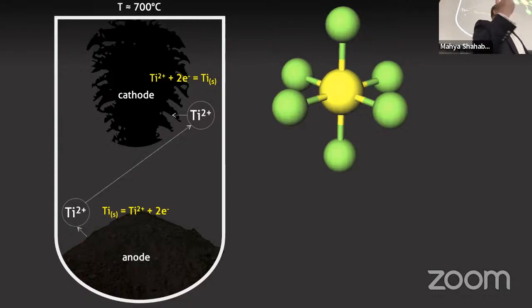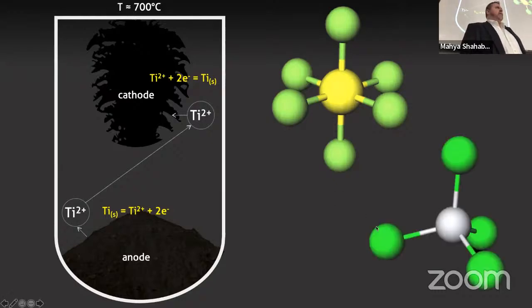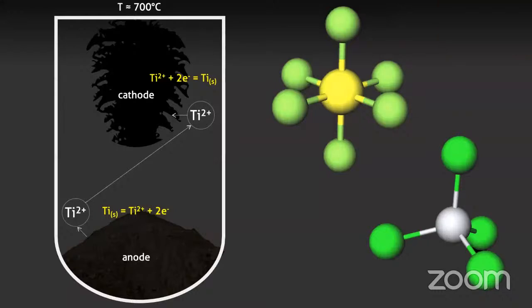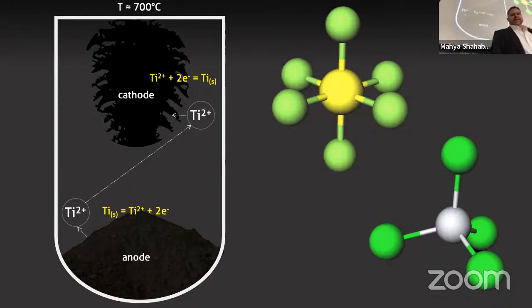So it's actually, you're going to see TiCl6, depending on where we end up in the final stage, or we can also see octahedral. I mean, we either have the octahedral, which is the first one, or we can have the tetrahedral coordination. This coordination is the key method by which we're hoping to use at least one of our probes to understand the composition. That probe being looking at the bond lengths between the titanium and the chlorine and seeing how those vibrations are detectable, kind of the same way that people do it in a lot of other pieces.